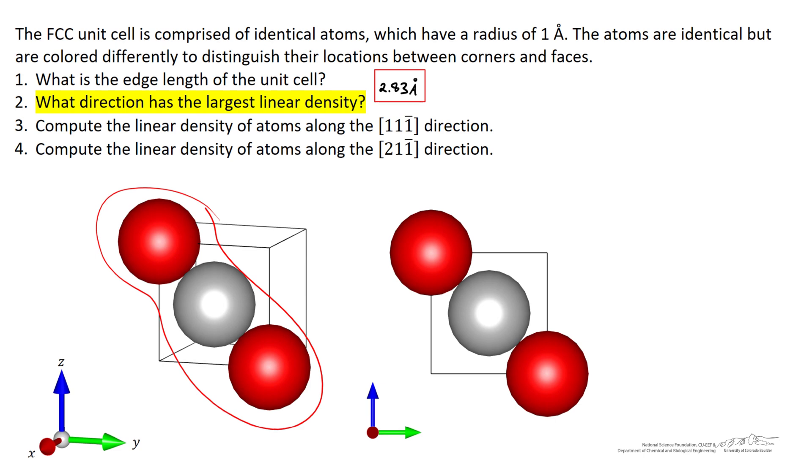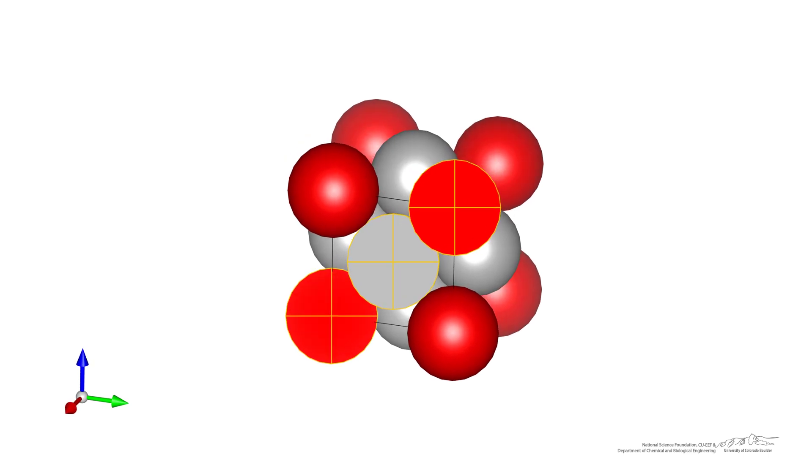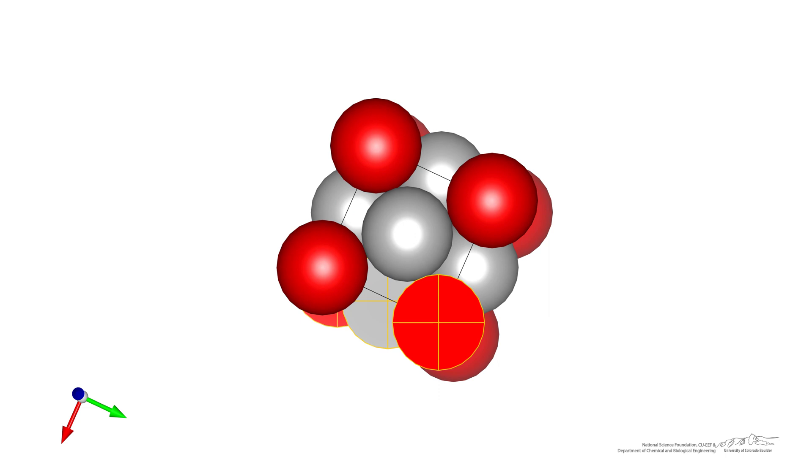In this case the direction that we're looking at would be as shown which is going to be 0 in the x direction because it's parallel to the front face. And we're going to move over one unit in the y direction so we've got 0, 1 and in this case a negative 1 in the z direction so I'm going to draw this vector as [0, 1, -1]. We'll get equivalent answers for the [0, 1, 1] direction, it's just the diagonal on the other side.